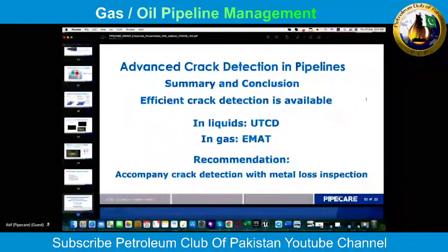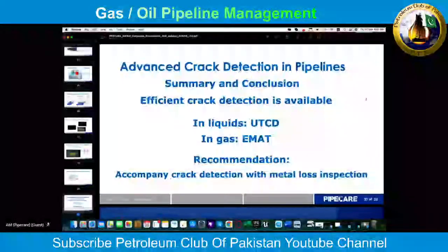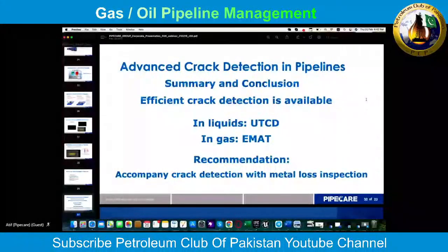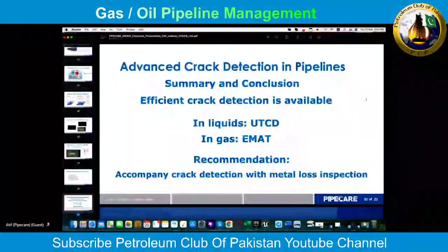We looked in the data, we looked at these features where they didn't find what we told them. And it was obvious that exactly what I explained had happened: these were metal loss features with a sharp edge, and this was interpreted as a crack. And when we did, again, the obvious, we reanalyzed the crack detection data. We compared with the inspection of the metal loss features, and afterwards, the hit rate was 95%. So therefore, the recommendation is that every crack detection inspection is accompanied with a metal loss inspection. Next.